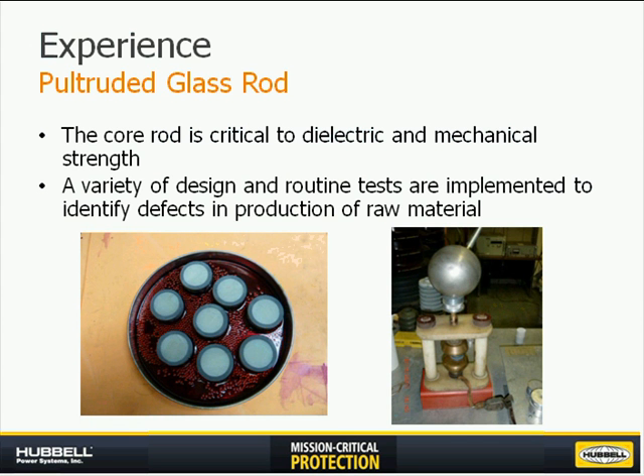Of course, if you have holes or fibers in your rod that do not get wet out by resin, that of course creates a path for electrical current to travel. So the dye penetration essentially checks for holes, and as you can see here in the photo, after you mold, it of course checks for cracking across the rod that can occur due to the thermal shock experienced during the molding process, and it also checks for cracking due to the crimping process, which we will look at in a second.